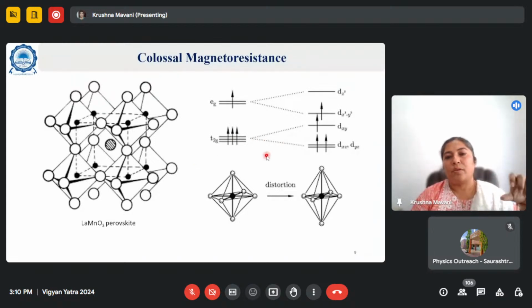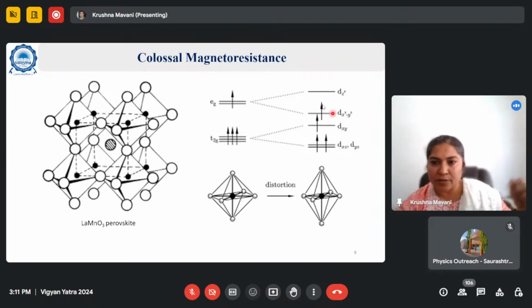Now, because of the crystal field effect in the surroundings, it will further split up like this. So these are known as t2g orbitals. They are dxy, dxz, dyz. In eg orbitals, they are slightly higher energy states. And electrons fill up like this and show the structure, because it is a lattice and electrons are actually correlated.